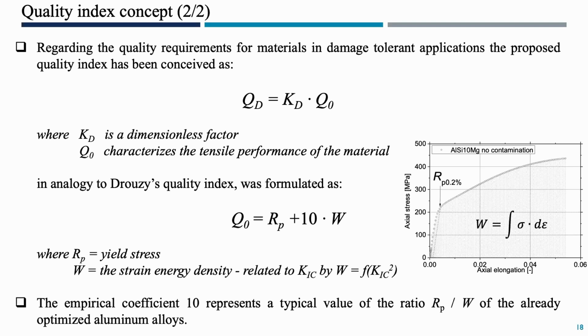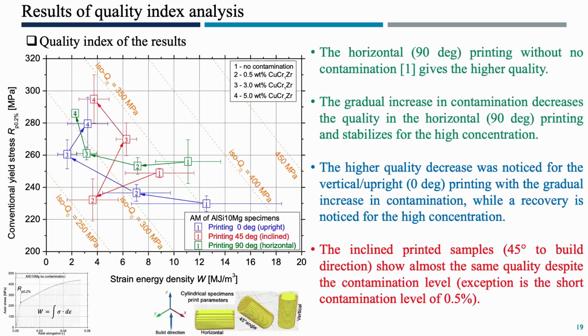So in this regard, we have used this kind of quality index to interpret all the tensile mechanical performance of the printed jobs. And as you can see, these are the results of the quality index. I will go step by step, showing that this is a diagram of yield stress over strain energy density. And of course, these dotted lines are the iso-quality curves. Starting from the 90 degrees, this is without any contamination, and with increasing contamination, you see that the quality slightly decreases.